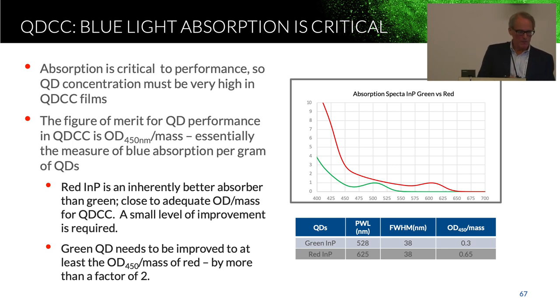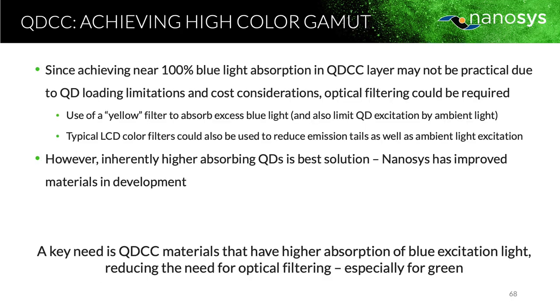So what can we do about that? We can do a couple of things. One is you can do optical filtering. One thing you can do is put what's called a yellow filter. It's called a yellow filter because it appears yellow, but it actually absorbs blue light. And if you put that over the entire display, it can take care of the blue light emission from the red and green subpixels, but the blue is so intense it still makes it through that. That's one way.